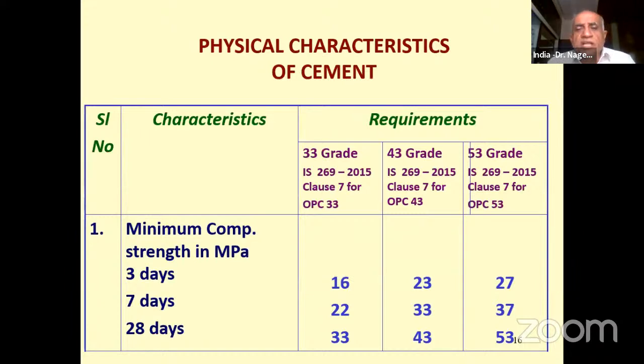Now, let us come to the requirements as per relevant codes. IS 269 gives the requirements for 33 grade cement, 43 grade cement, and 53 grade cement. So minimum compressive strength for 3 days, 7 days, and 28 days is given here: 16, 22, 33 for a 33 grade cement, 23, 33, and 43 for a 43 grade cement, and 27, 37, and 53 for a 53 grade cement.